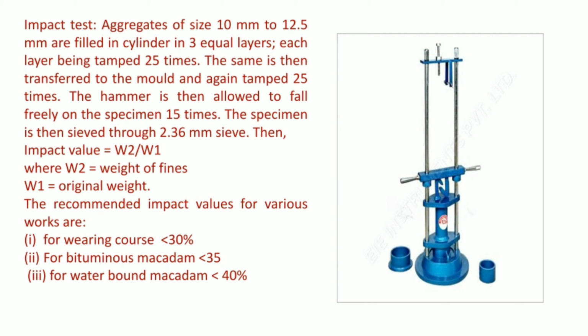The recommended impact values for various works are: for wearing course, it should be less than 30%. For bituminous macadam, it should be less than 35%. For waterbound macadam, it should be less than 40%.